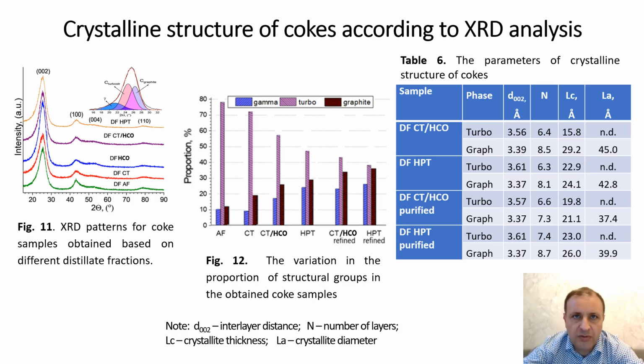From the deconvolution of the 002 peak, 4 structural components were identified. Graphitic domains are formed by an ordered packing of flat polyaromatic layers, like graphenes. Domains with a turbostratic packing are characterized by a less regular structure. Based on the deconvoluted XRD patterns, the proportion of the structural components and the crystalline parameters were calculated and shown in figure 11. Figure 12 shows that coke samples consist predominantly of turbostratic and graphitic crystallite domains.